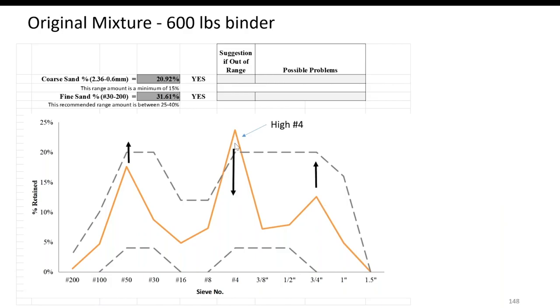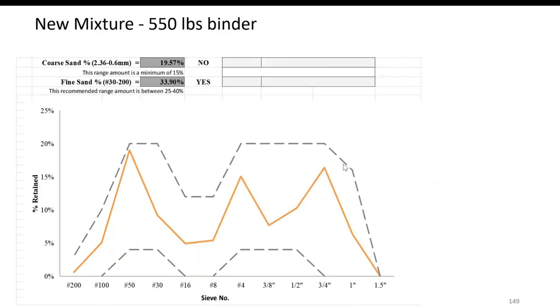No, not a problem. I'm going to lower this down and raise these up. That's all I did. Lower it down and raise them up. And as soon as I did, I knew I could save them on binder. I knew if they were happy before, that I could reduce the binder and they're still going to be happy.